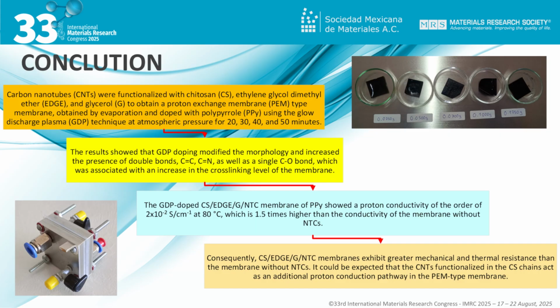membrane. The membranes doped by polypyrrole using the glow discharge plasma technique showed a proton conductivity of the order of 2 times 10 to the minus 2 Siemens per centimeter to the minus 1 at 80 degrees Celsius, which is 1.5 times higher than the conductivity of the membrane without carbon nanotubes. Consequently, the membranes exhibit greater mechanical and thermal resistance than the membrane without carbon nanotubes. It could be expected that the carbon nanotubes functionalized in the Chitosan chains act as an additional proton conduction pathway in the proton exchange membrane type membrane.